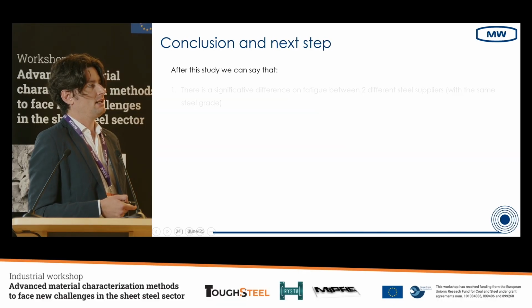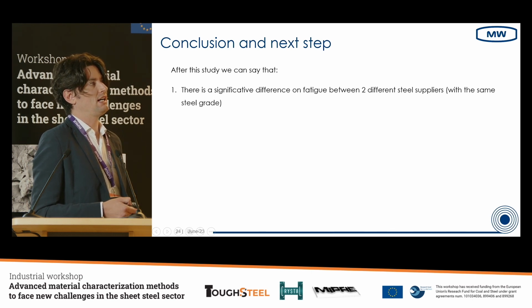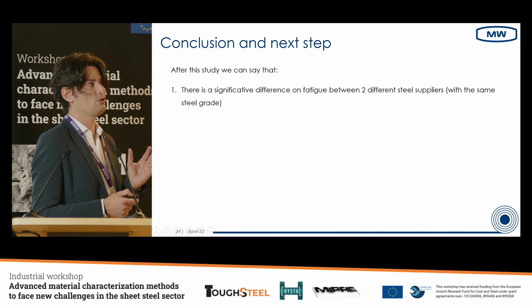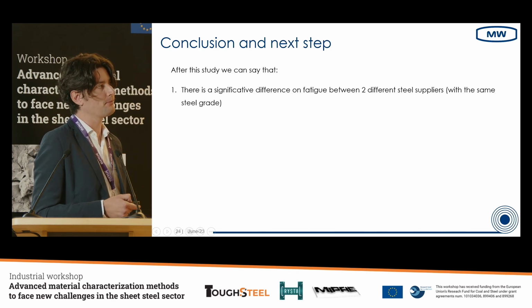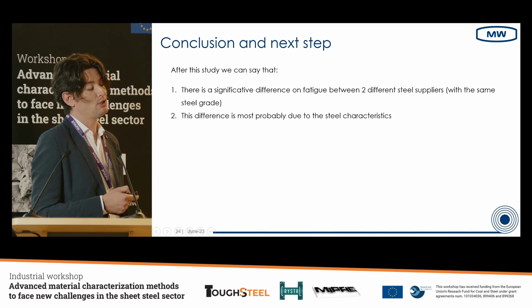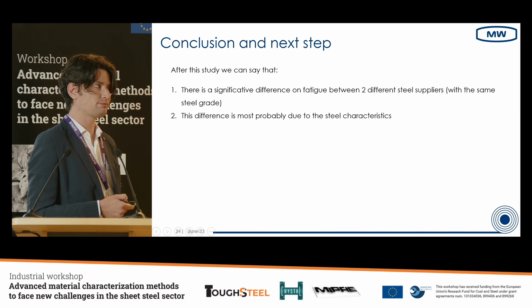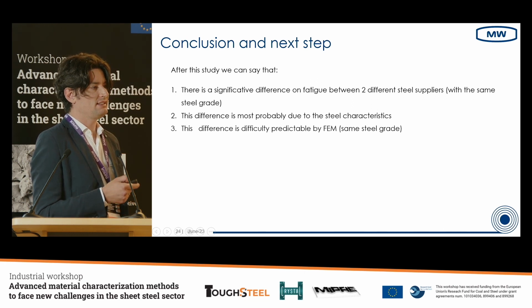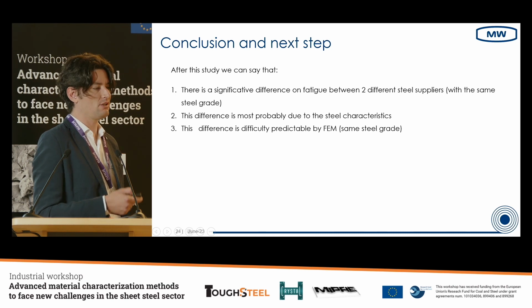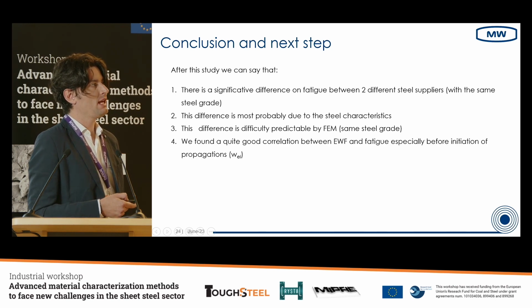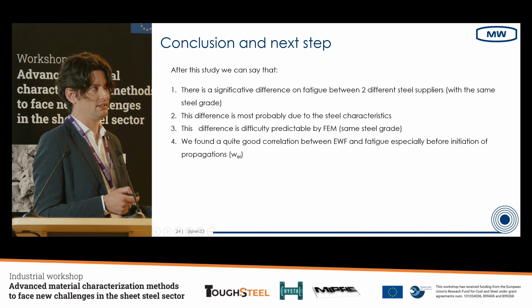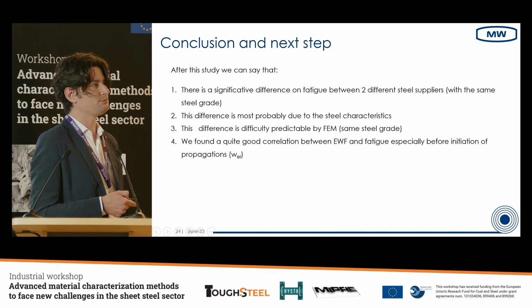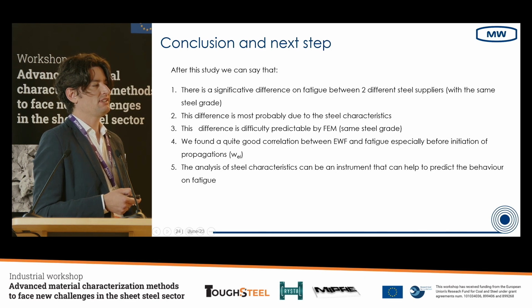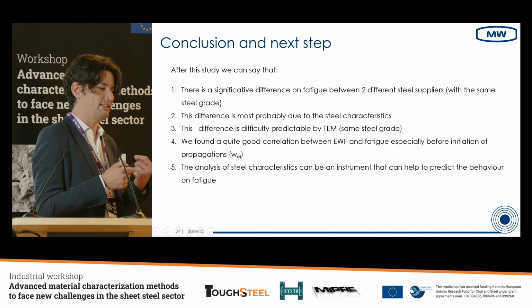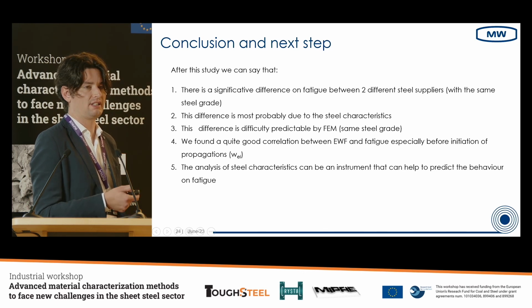So, concluding, we observed a significant difference between two different steel suppliers with the same material grade. The difference is mostly due to the steel characteristics. And this difference is not predictable by the FEM simulation if we consider it as the same steel grade. And we found quite a good correlation between the essential work of fracture at the initiation and the fatigue. The analysis of these characteristics can be an instrument that can help to predict the behavior in fatigue.